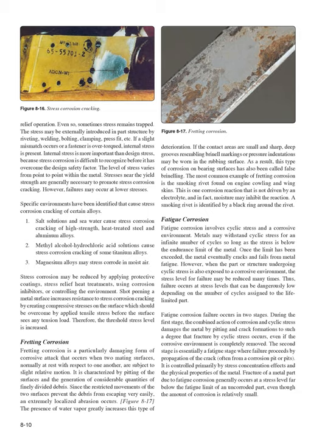Stress corrosion may be reduced by applying protective coatings, stress relief heat treatments, using corrosion inhibitors, or controlling the environment. Shot peening a metal surface increases resistance to stress corrosion cracking by creating compressive stresses on the surface, which must be overcome by applied tensile stress before the surface sees any tension load. Therefore, the threshold stress level is increased.